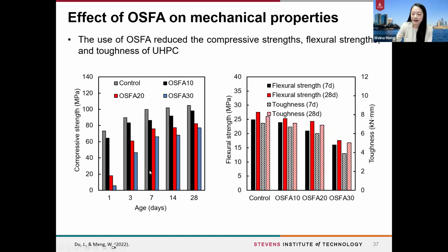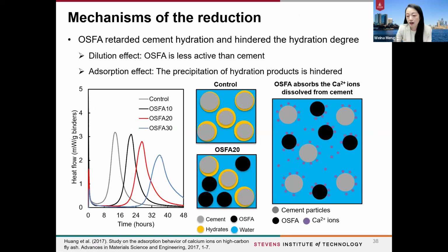So as expected, if we use the OSFA to replace cement, both the compressive strength and the flexural properties are significantly reduced. The reason is that the OSFA retards and hinders the cement hydration due to two effects. First is the dilution effect. OSFA is inert. It is much less active than the cement, so there is much less cement hydration happening there. And the second is the adsorption effect. As the OSFA has very high surface area and high carbon, it absorbs the calcium ions dissolved from the cement. So that will hinder the precipitation of hydration products.